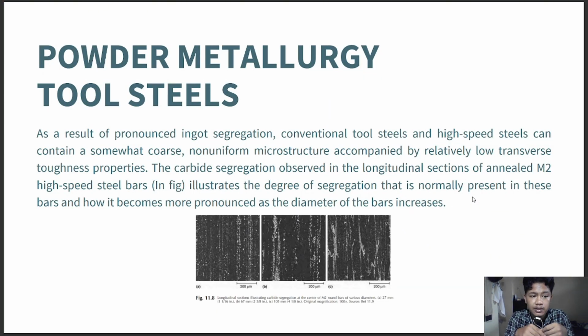Powder metallurgy tool steels. As a result of pronounced ingot segregation, conventional tool steels and high-speed steels can contain a somewhat coarse, non-uniform microstructure accompanied by relatively low transverse toughness properties. The carbide segregation observed in the longitudinal section of annealed M2 high-speed steel bars, like this picture, illustrates the degree of segregation that is normally present in these bars and how it becomes more pronounced as the diameter of the bar increases.